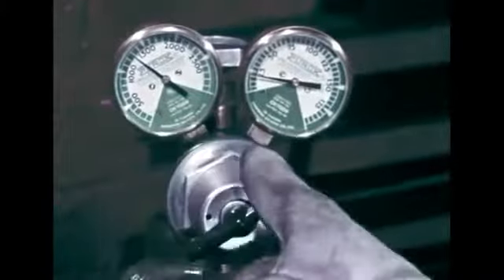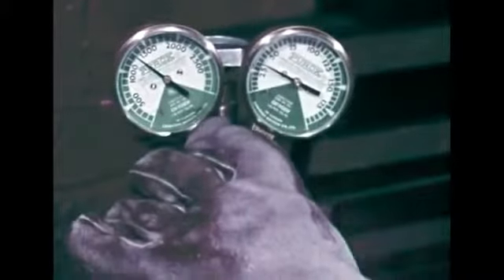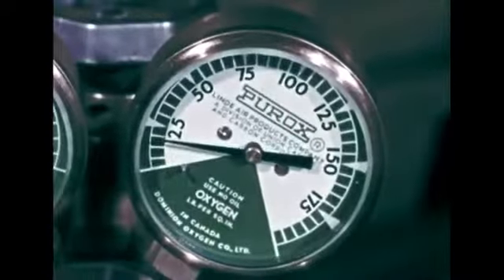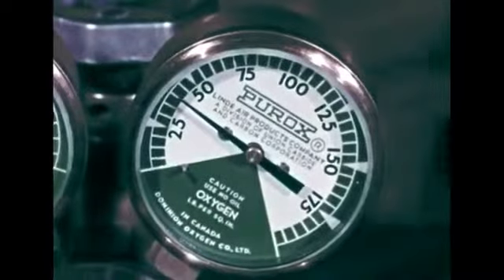Now, increase the oxygen pressure to 35 pounds per square inch and increase the angle between nozzle and plate to approximately 10 degrees. This groove is about 1/2 of an inch wide and 3/8 of an inch deep. Change the oxygen pressure as necessary for the width and depth of groove desired.